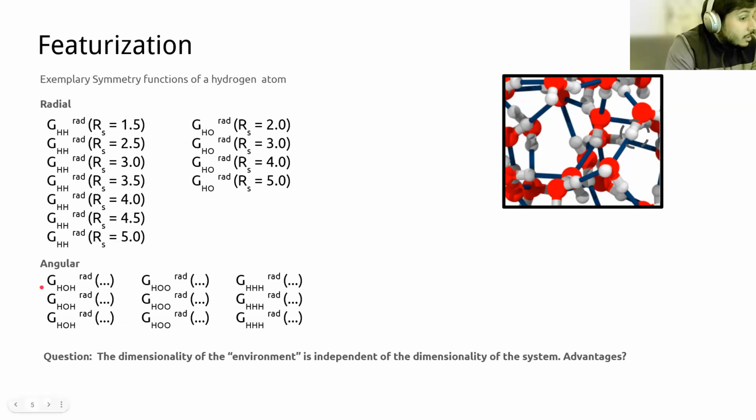And again, you will compute the angular symmetry functions, again, pardon, this should be ANG instead of RAD. In that case, what you will be doing is instead of computing distances, you would be computing the dot product between two position vectors, and that gives you basically a sense of what kind of triplets you form, what are the angles that you generally probe, and you can construct these angular symmetry functions to either select for particular angles, that you can ask how many 60-degree angles are there, or you can probe them in a way that they include, let's say, sums of all sorts of angles, and that's your choice.